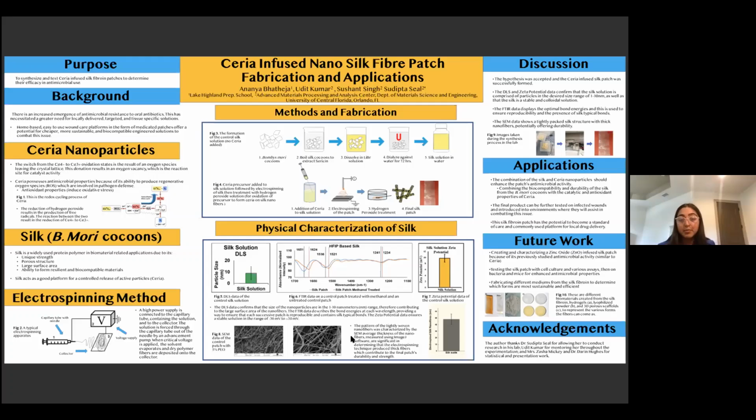And the last part of the characterization was the SEM images, which you can see down here. What we're really looking at is how tightly packed these fibers are and how thick these fibers are. These 2 images show you a little close-up of these fibers being so packed together so tightly, which makes them strong and, again, adaptable and biocompatible, which is what we want. And then this graph shows you the thickness of the silk mat, and it reached our goal.